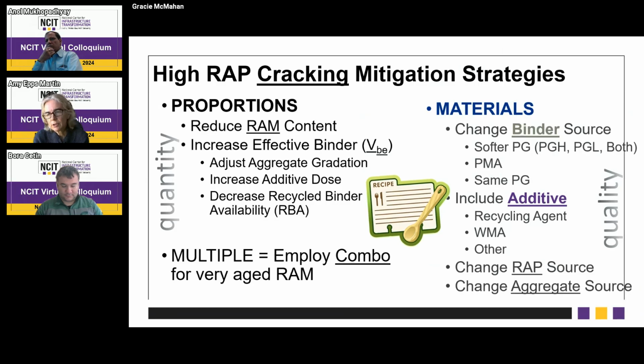So what are these different cracking mitigation strategies? I mentioned some of them in the New Jersey part of the presentation, but basically, what can we change about the recipe for our hot mix asphalt? We can change the materials, and that has to do with the quality of the materials. So we can change the binder source. We can make it a softer binder, either at the high temperature end, the low temperature end, or both. We can add a polymer modified asphalt, or we can just simply keep the same PG performance grade, but change the binder source. We can also include an additive like a recycling agent or a warm mix additive.